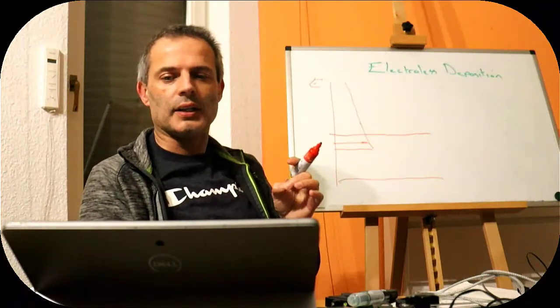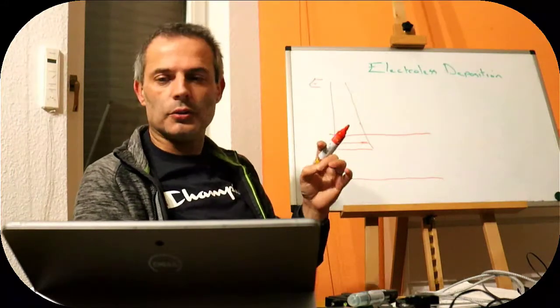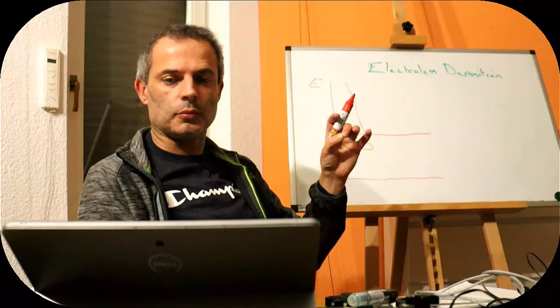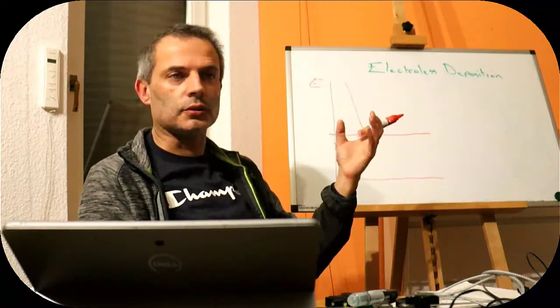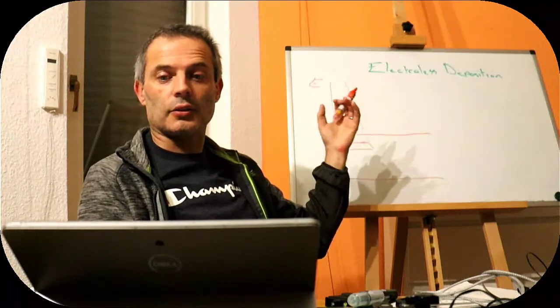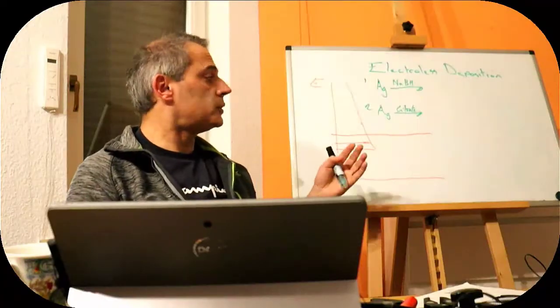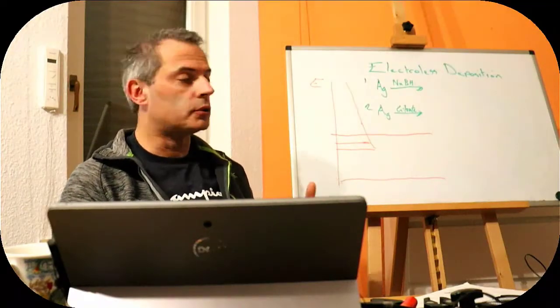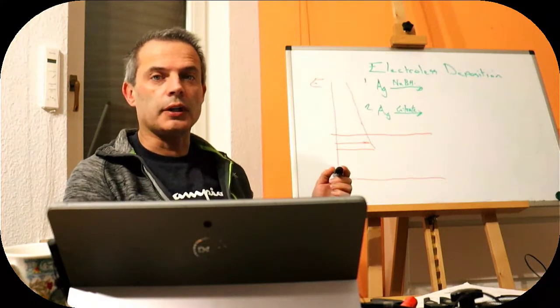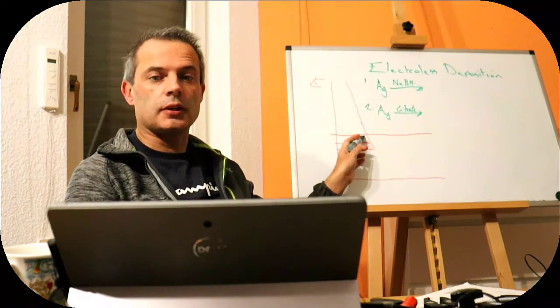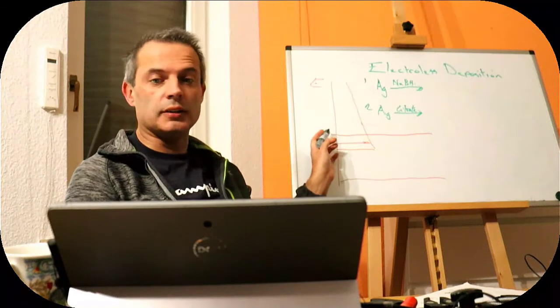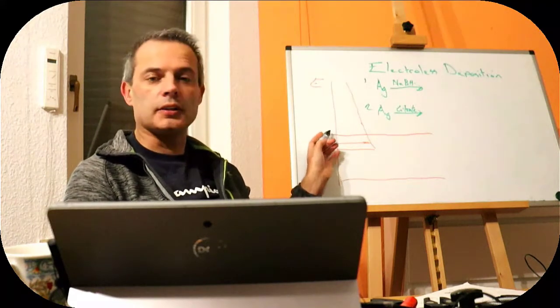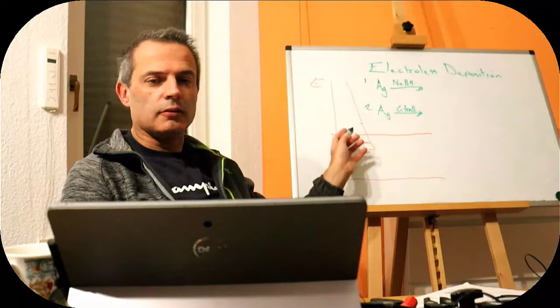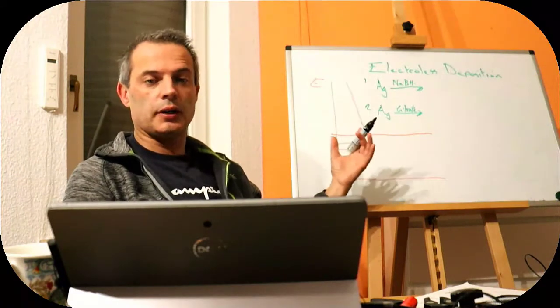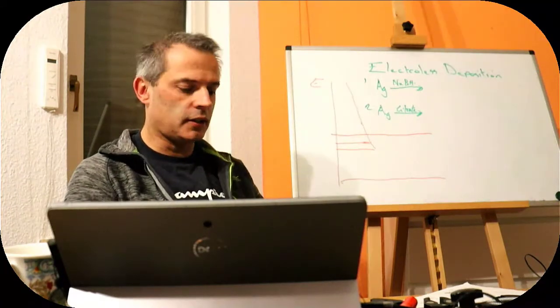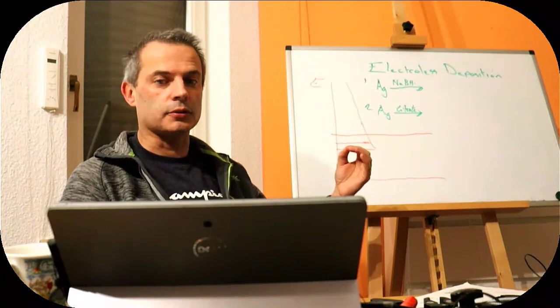But we can also help it a little bit further, and we usually do that by putting some seed crystals of metal on our surface first. So what we can see here is that ideally, if we want to coat something rather than to make new particles, we should stay as close to this solubility limit line here, or in this case the reducing potential just to make the metal, and we can see that if we even make particles.